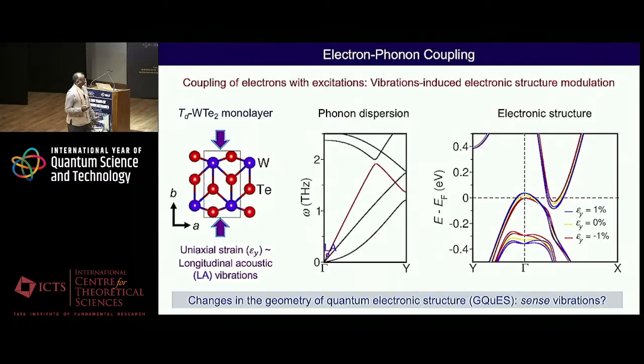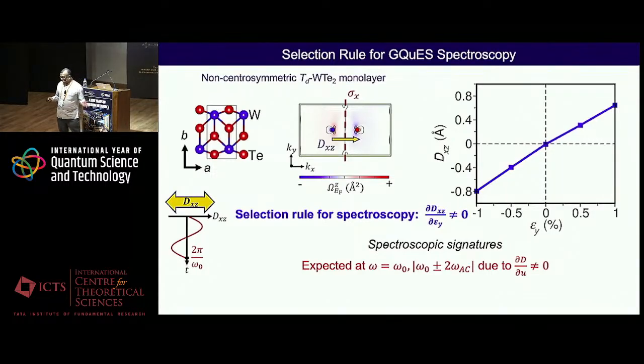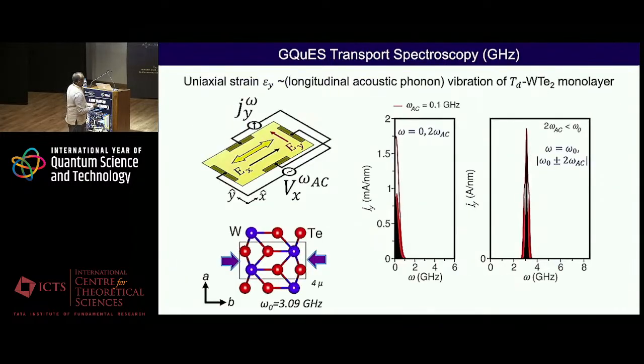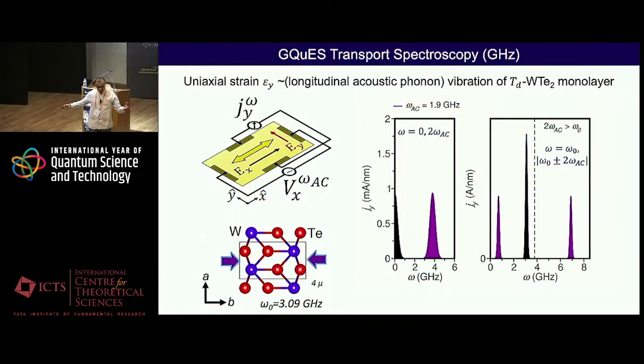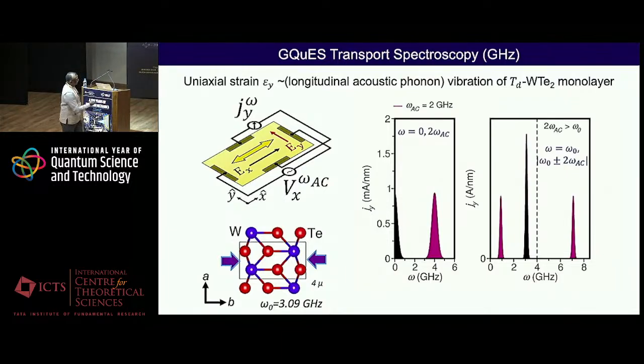We demonstrated this with specific predictions for materials that are available in the lab today, and given the limitation of time, I'll quickly go through it. First we worked out non-centrosymmetric tungsten telluride, and we predict that the Berry curvature dipole moment is linearly proportional to strain, and that gives rise to the spectrum shown here. If you change the applied AC frequency, the Stokes and anti-Stokes peaks move around. So there is additional control over the spectra. By changing the driving frequency, you can monitor the Stokes and anti-Stokes peaks and then confirm the vibrational frequency.